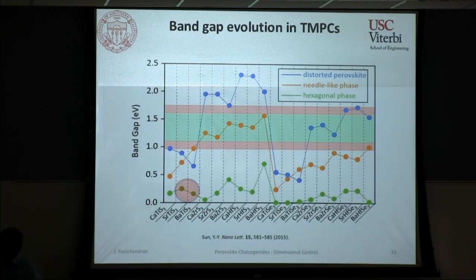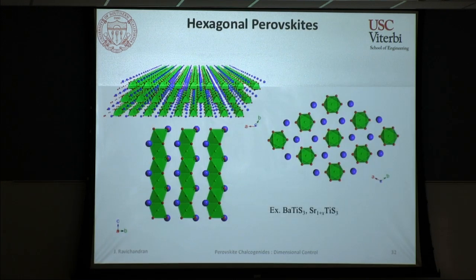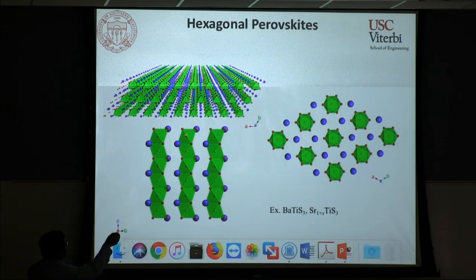As titanium is much smaller than zirconium, the chances that you would stabilize this hexagonal phase over the other phases is very high. So it's a good compound to study. So what are these hexagonal perovskites? I'm using the term hexagonal perovskite, which any true crystallographer will hate, but this is just to show that it has octahedra that are connected and form the hexagonal structure.